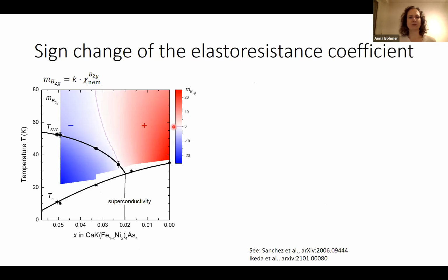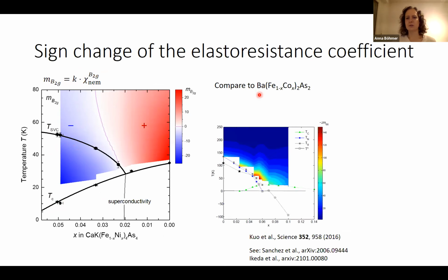And I will do that first of all by plotting it in a color plot here over the phase diagram. Notice I flipped the phase diagram. So here's the magnetic phase. We see a sign change, but the nematic susceptibility does not change sign. This has to be the proportionality constant. If we compare that to the cobalt barium 122, there's no sign change here, but there's a significant change of magnitude of this elastoresistance coefficient.